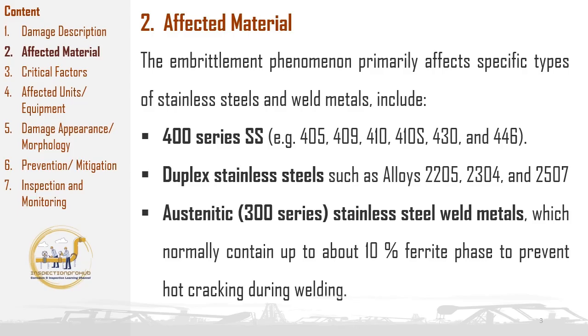In this temperature range, the balance of ferrite and austenite phases can be disturbed, leading to the precipitation of embrittling phases, particularly the sigma phase, which significantly reduces toughness and ductility. This makes duplex stainless steels more susceptible to cracking and failure if they are exposed to thermal cycling or improper welding conditions that promote these phase changes.